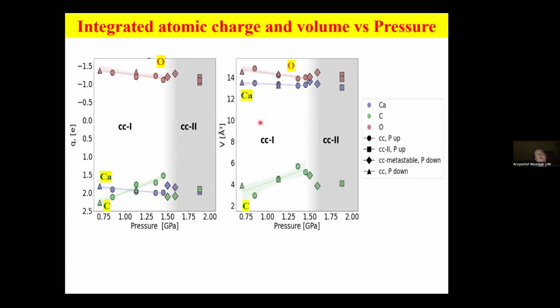We can actually deconvolute equations of state into atomic contributions. As you can see here, we are getting the dependence of the volumes of atomic basins as a function of pressure. And we have negative compressibility of the carbon atom, because the volume is increasing with pressure, and normal compressibilities of oxygen and calcium.